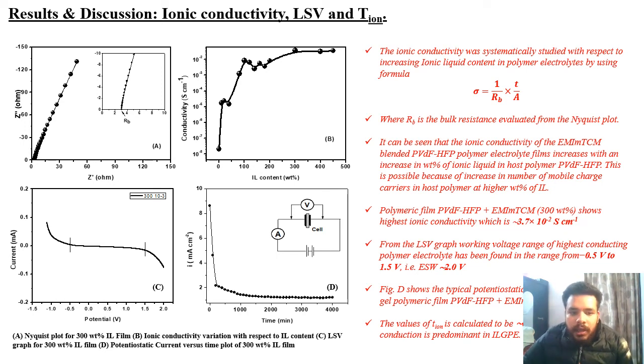And here you can see in the lower left corner a graph between current and potential. This is the LSV graph of the highest conductivity film. Here you can see that it is stable from minus 0.5 to 1.5 volt, that is almost 2.0 volt. So we can say that the electrochemical stability window of the 300 weight percent film is 2 volt.